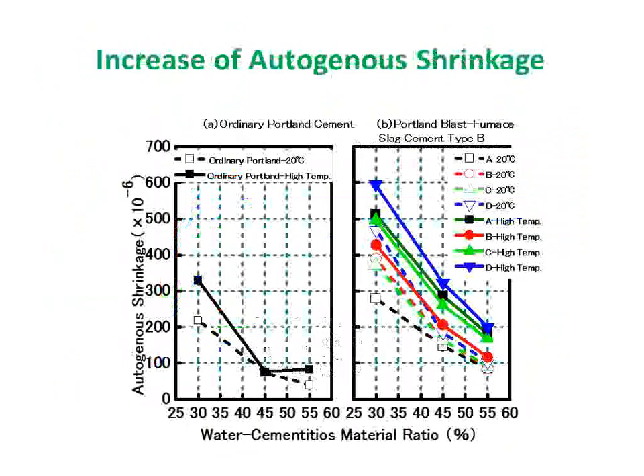And this is the data of the autogenous shrinkage. This is ordinary Portland cement. This is the Portland blast furnace cement. It's quite obvious. Depending on the kind of the cement or condition, it's a different value, but it's quite obvious. The autogenous shrinkage of the blast furnace Portland cement is larger than the ordinary Portland cement. So it means that if you utilize this kind of cement, you have the possibility to have cracks.